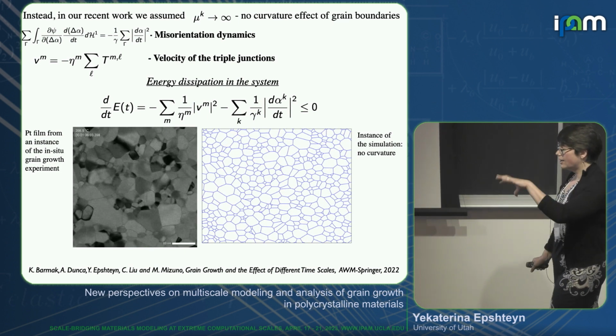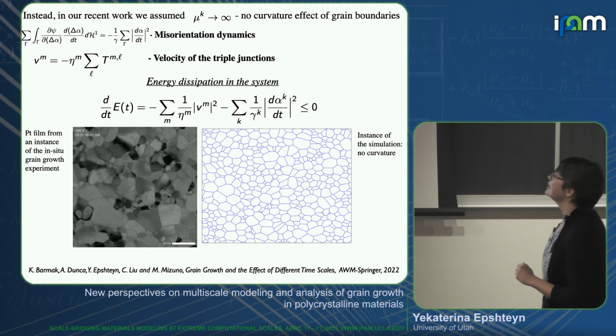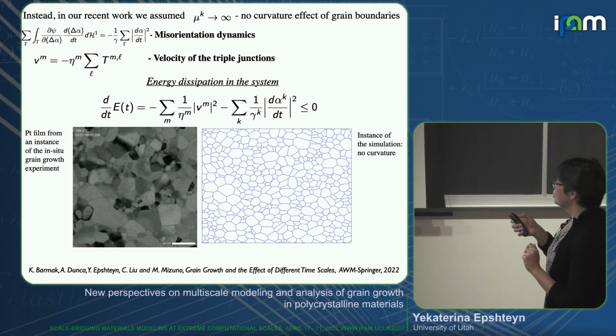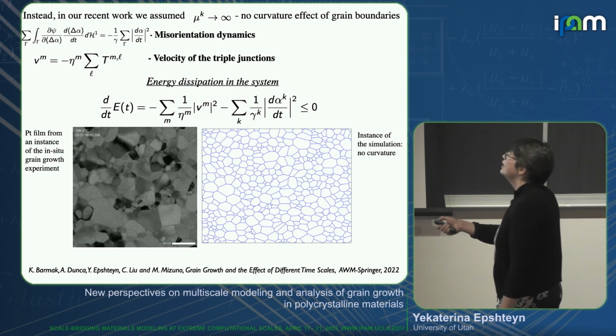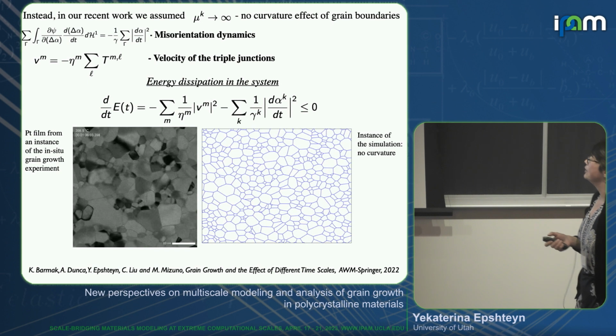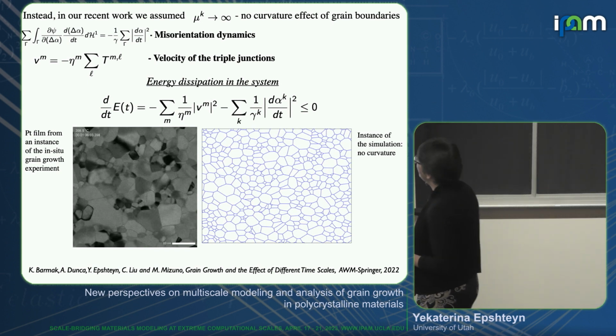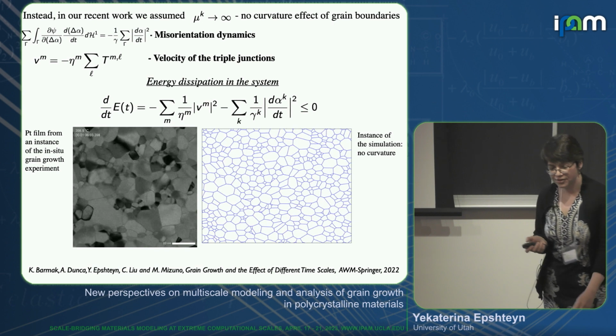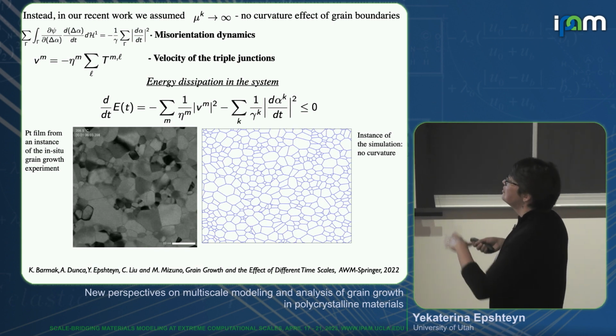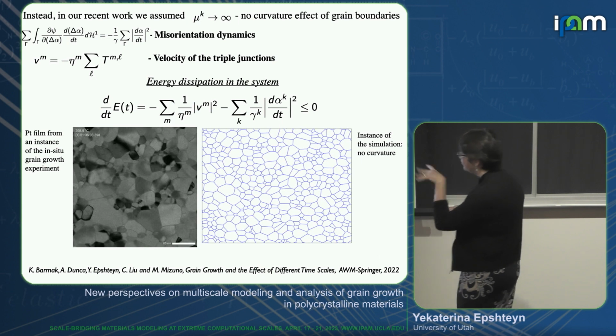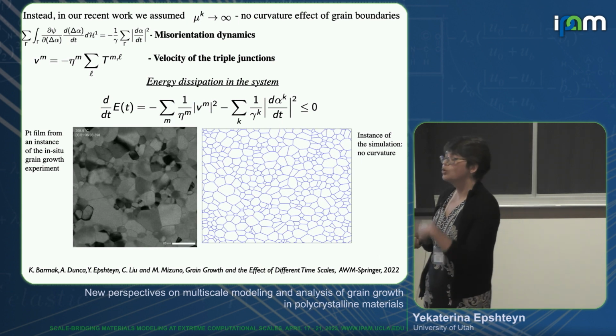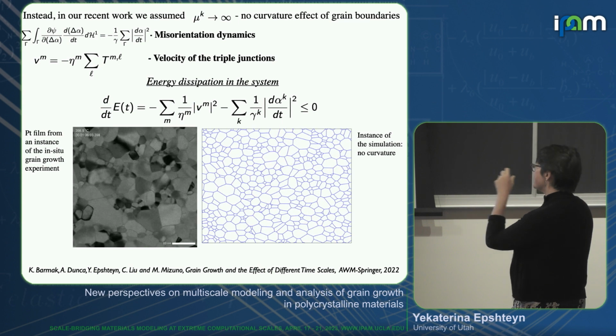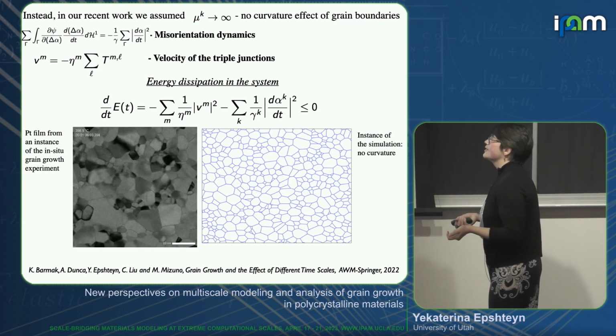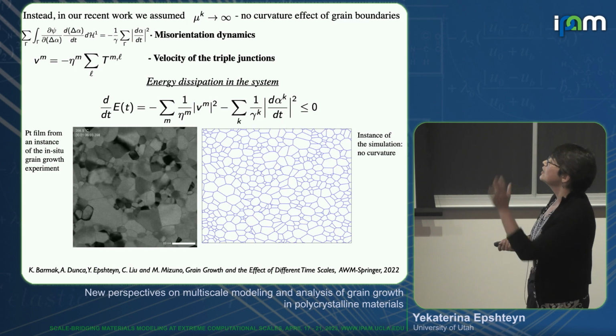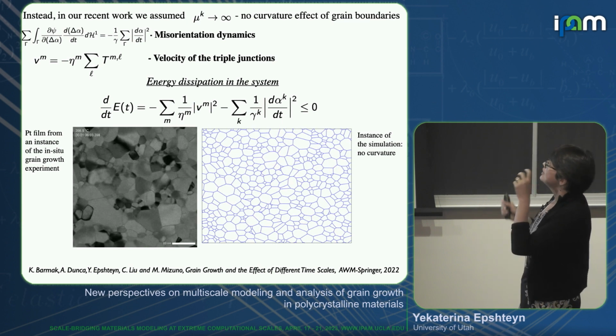So we had a few goals with that. First of all, we wanted to isolate and understand better the effects of the dynamics of misorientations and dynamics of triple junctions on grain growth. Also, once we relax dynamics of grain boundaries, the system changes from a nonlinear coupled PDE, ODE system to a nonlinear ODE. So it's a reduced system. It's a non-standard system of ODE. It's a constrained nonlinear ODE, but it's much simpler.